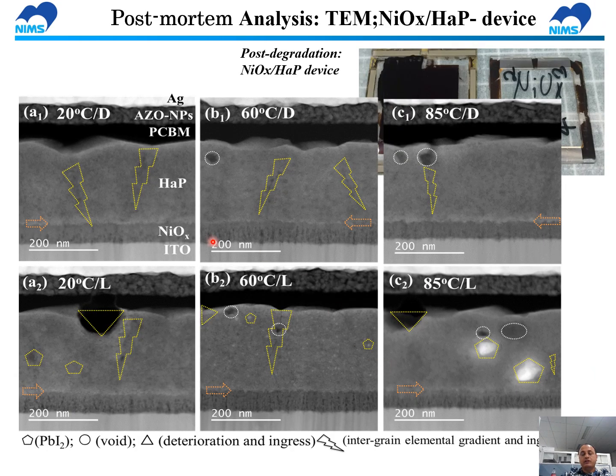However, if we compare the device with nickel oxide, it is comparatively stable, and of course, if we compare dark and under light, the deterioration rate is much faster under light. We can see the interfacial deterioration and bulk formation of lead iodide under higher thermal stress. And of course, the nickel oxide is comparatively stable, which explains the device degradation trend.